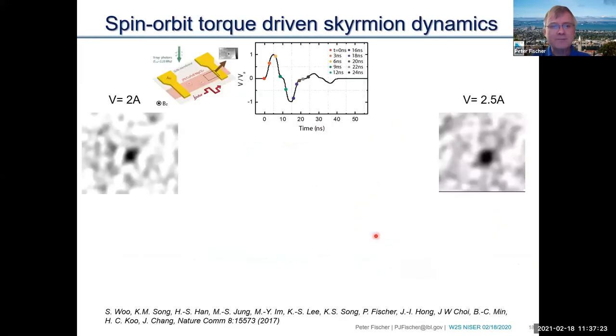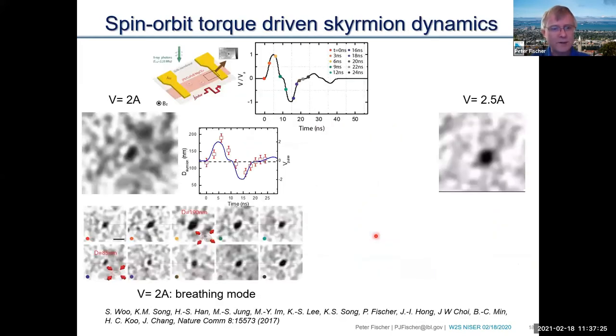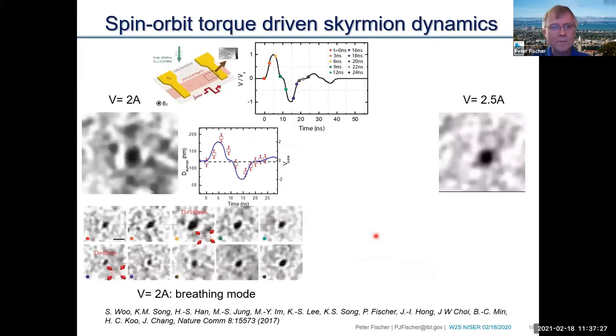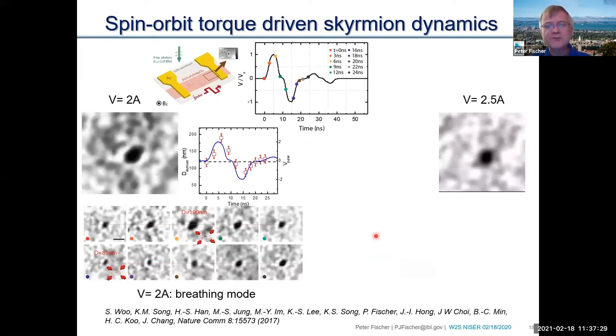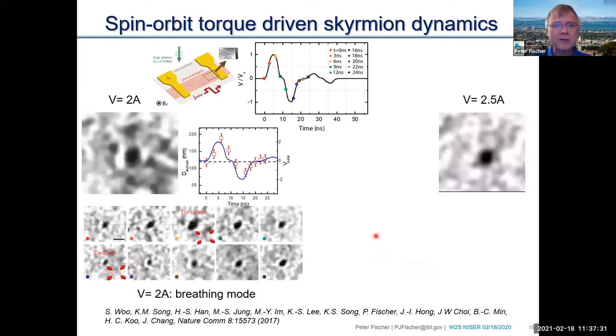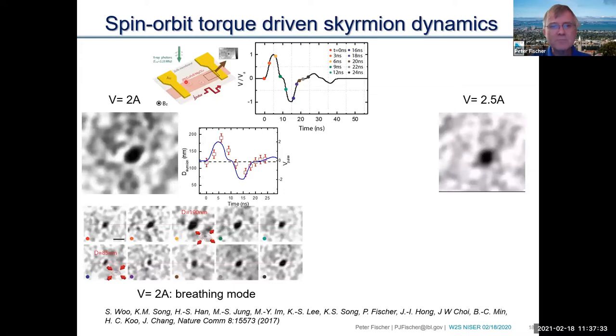Okay, and this is one example which we have done, and this was done together with Seonghoon Woo a while ago. We looked into spin-torque-driven skyrmion dynamics. So what we did is we generated skyrmions in a platinum, iron boron, magnesium oxide kind of thin layer structure by applying a certain pulse sequence. We were able to generate, and you can see this little dot here. This is one of the skyrmions, the one that I showed you earlier in the schematics. And then we basically excited them with a pulse. And this is the pulse sequence that we excited with.